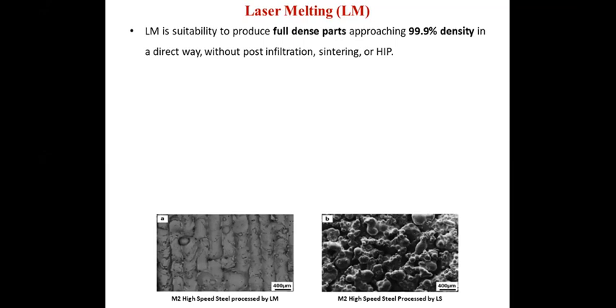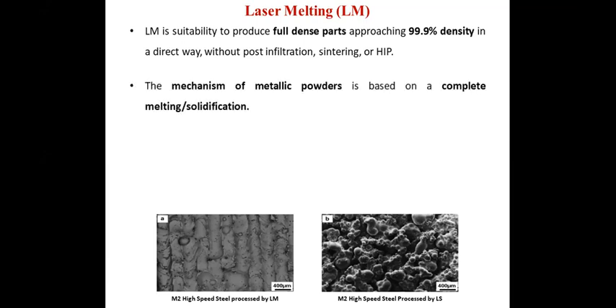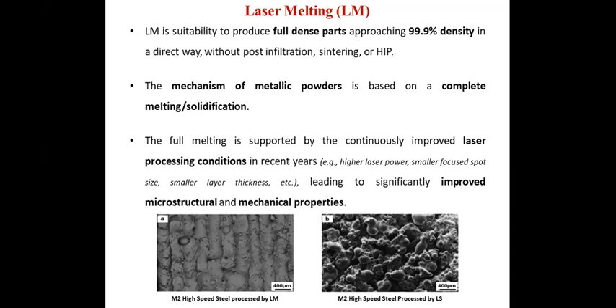And then we move on from laser sintering to laser melting, where parts could be produced with 99.9% density in a direct way, without the post infiltration or sintering that we need for laser sintering. The mechanism for metallic powder is based on a complete melting and solidification. The full melting is supported by continuously improved laser processing conditions, such as higher laser power, smaller focused spot size and smaller layer thickness, leading to significantly improved microstructural and mechanical properties. The microstructure on the left-hand side shows laser melting, and the right-hand side picture shows laser sintering.